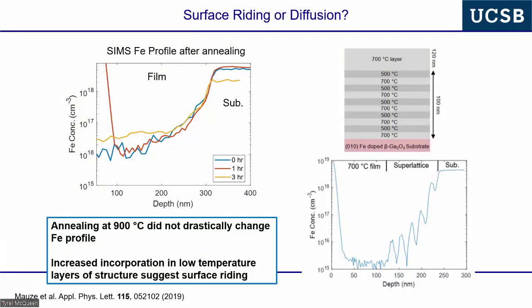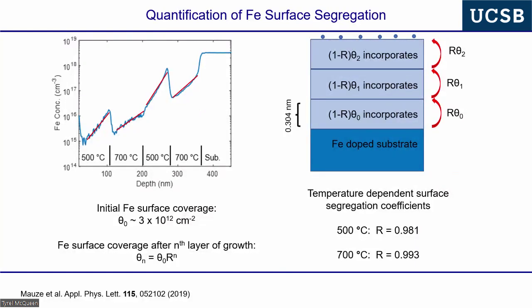So what we then looked at is that if we grow superlattices at high temperature, low temperature, high temperature, low temperature, what you actually find is that when you go to the low temperature layer, you have high impurity concentration. When you go to the high temperature layer, you have low impurity concentration. And this is characteristic of surface segregation. So on the substrates that we have, there's free iron on the surface, and it's riding the surface with a very, very low incorporation coefficient. So low iron concentration at high temperature growth, high iron concentration at low temperature growth. It's decreasing because we have weak incorporation here, we have more incorporation here, and we're actually consuming the material.